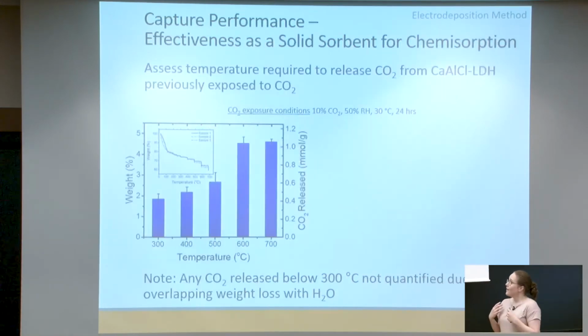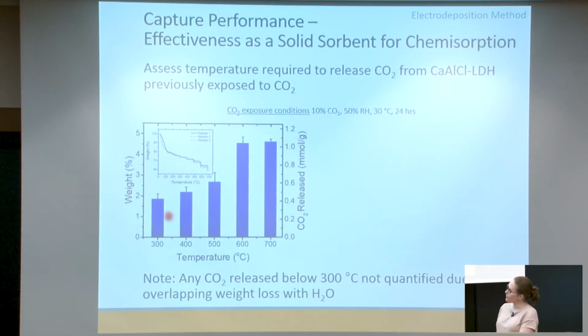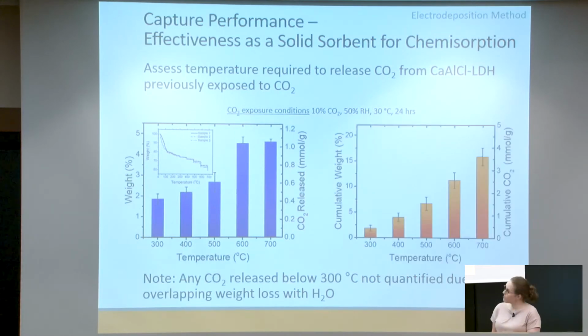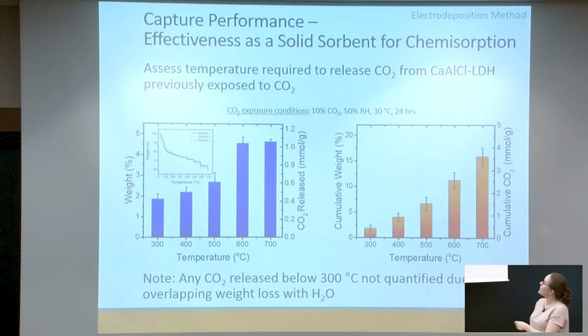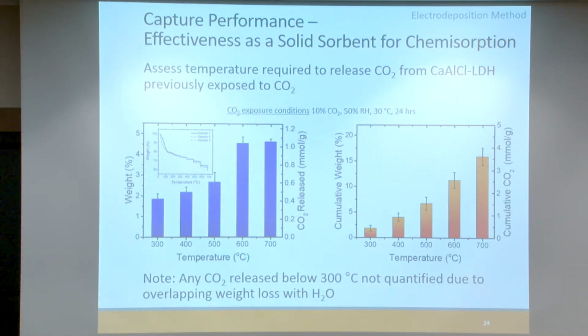Now, what we've done here is, if you heat to 300 and hold for a period of time, then this is how much CO2 has come off the sample. If we heat to 400, go from 300 to 400, this is how much CO2 comes off, and so forth, where the weight corresponds to the CO2 released. And therefore, we can benchmark what is the capture capacity of this layered double hydroxide. And what we find out here is about 3.5 millimoles of CO2 per gram of the sorbent.